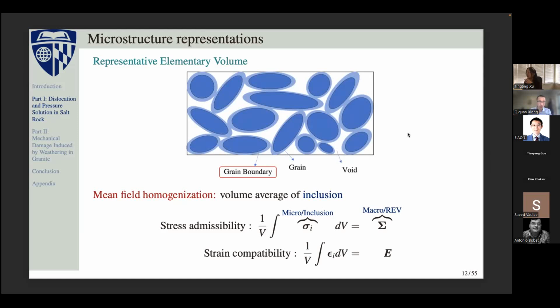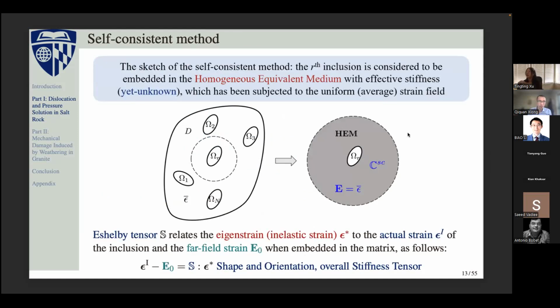So with these two fundamental equations, we're going to choose one of these homogenization methods, the so-called self-consistent method. This method is particularly designed for materials such as halite, because it's a polycrystalline material, and there is no dominant material or dominant phase inside it. We consider each single crystal embedded in a so-called homogeneous equivalent medium, and we calculate the overall response by considering all the different crystals inside it.